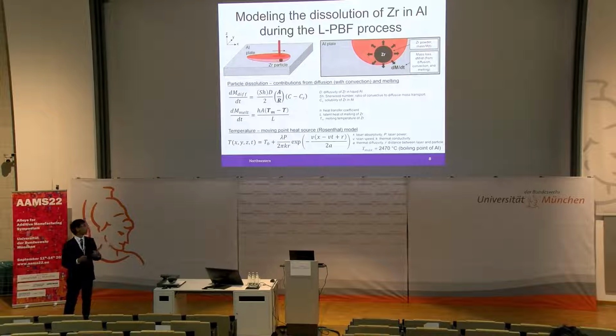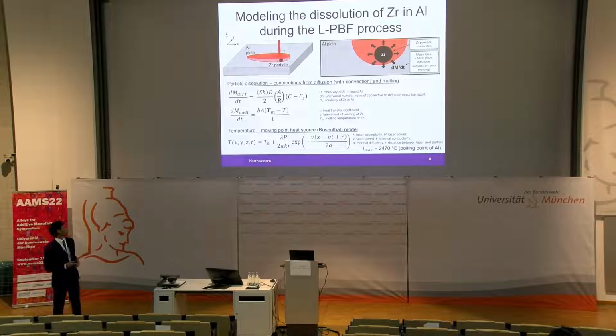At every single time step in the model, the zirconium particle loses some mass, and it will do so by two mechanisms. The first we consider is the effect of diffusion of zirconium from the solid zirconium particle into the liquid aluminum melt pool. We consider this by a Fick's first law type equation, which we modify by this Sh term, the Sherwood number. This estimates the effect of Marangoni flow in the melt pool. The second term, this melting term, occurs when the zirconium particle is hot enough such that it can melt. And this is simply the melting rate of a spherical particle.